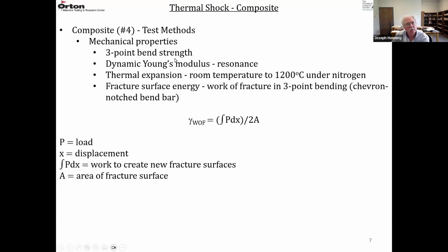So they measured 3-point bending for the strength. They measured a resonance technique for Young's modulus. They measured thermal expansion from room temperature to 1200 degrees C in an inert nitrogen atmosphere. And for the fracture surface energy, they used the work of fracture test in 3-point bending, which is that chevron notch